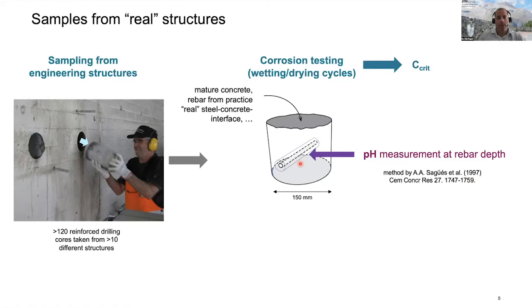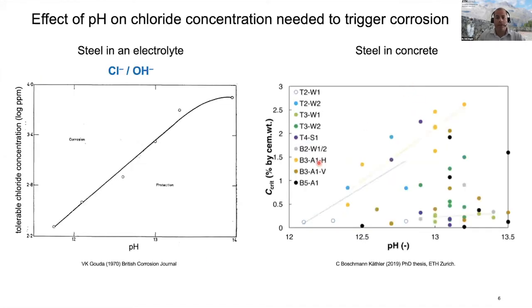So when we now compare the critical chloride concentrations from these cores, 120 cores taken from about 10 different structures, and we compare the pH and the critical chloride concentration, this is the type of result we can get. So you can see here the critical chloride content versus the pH, and you can see that we basically do not find such a generally applicable relationship as in the case of an electrolyte. But the different colors in this plot represent cores taken from different structures. And if you look at, for instance, the yellow ones, we can imagine that we have in this yellow structure such a relationship present. So when we increase the pH, we can also increase the critical chloride content. But for other structures, this doesn't hold at all. And if we take all structures together, we cannot see any systematic relationship in this case. In fact, for a pH of 13, there is a huge scatter in critical chloride content in these samples taken from structures.